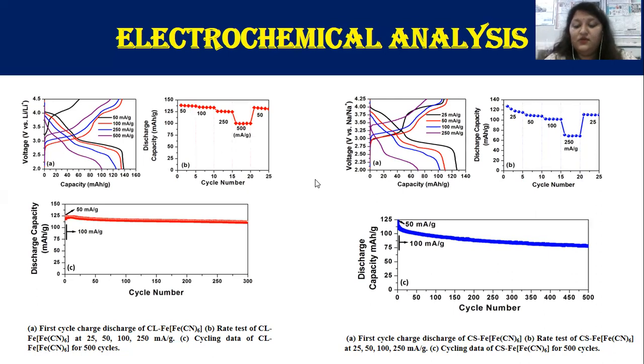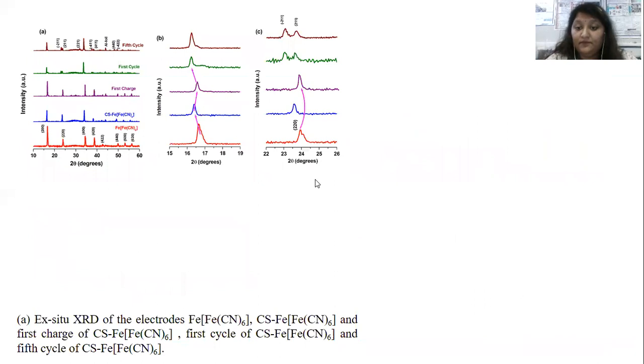In order to further advance the knowledge towards the cycling capacity and retention, the sodiated PBA cycling performance has been conducted and is given in figure C. You can see that the initial 2 cycles were done at 50 specific current, and from there we have done at 100 specific current. A 500-cycle data is shown, and a capacity of 78 mAh per gram was obtained at the end of 500 cycles with 70% retention. And it has been observed that the capacity decreases in the initial cycles, however, at the later stages, cycling stability improved significantly.